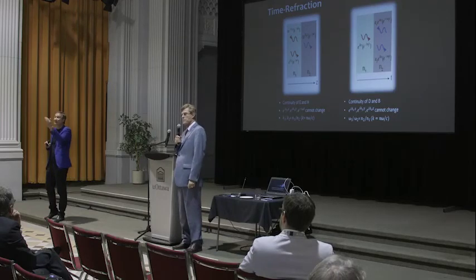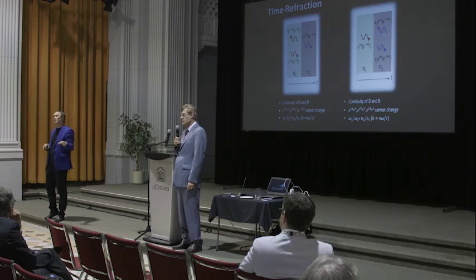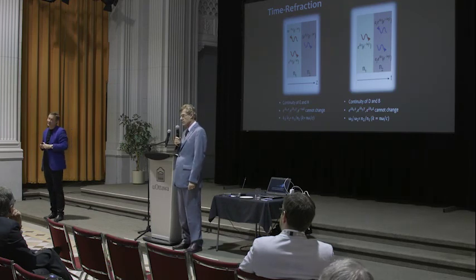But in principle, you're right, and of course, there is no one thing that would fit all sizes. But there are a lot of new opportunities here, because with gold, you're immediately stuck. It's not the most compatible, and 400 Celsius destroys it no matter what. Here, yes, there are challenges, but they can be solved. Like oxidation, for example. It turns out that you could place a protection layer and be completely resistant to oxidation. And we already showed this. But that's a valid comment, yes. We're not naive. We're looking at these other things to take care of to make it a real device. And what you mentioned is one of those.